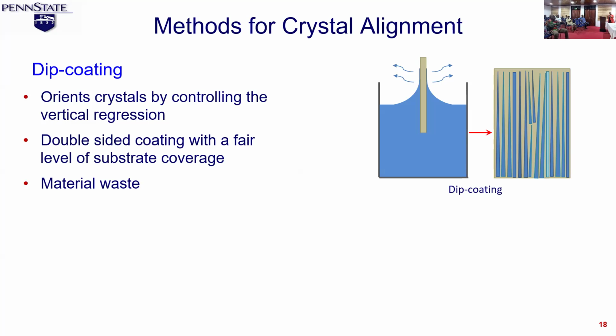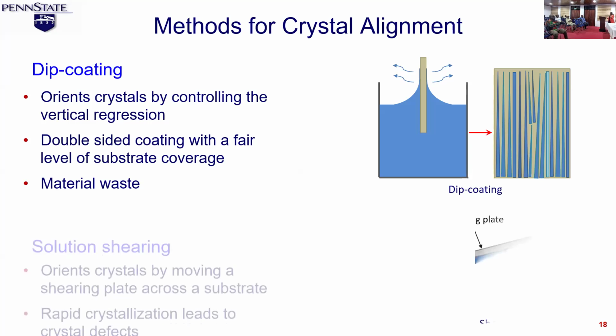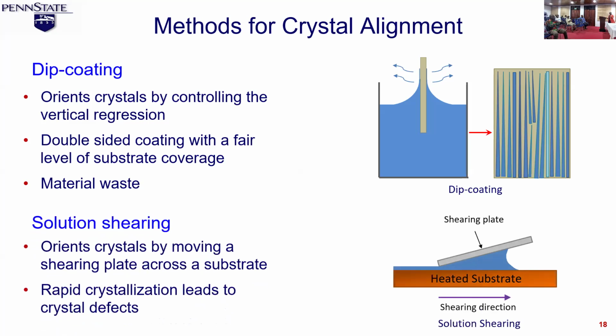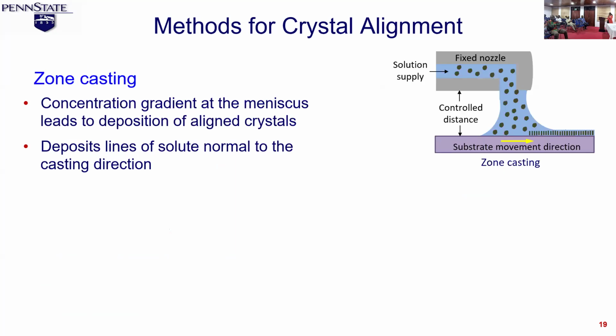The disadvantage of this method is that it wastes material, because you end up having crystals forming on both sides of the substrate, and you only need it on one side, right? Then we have solution shearing, where the substrate is heated, the solution is put on the substrate, and then the shearing plate is dragged across the solution, and that again orients the crystals. Again, this doesn't give you the best crystals, because there's rapid crystallization that happens, and when crystallization happens rapidly, you tend to have gaps in between the crystals.